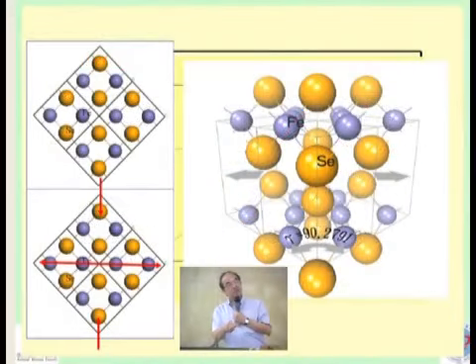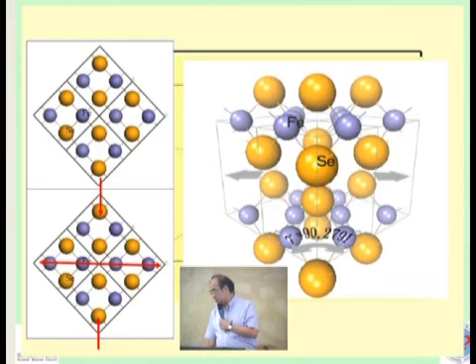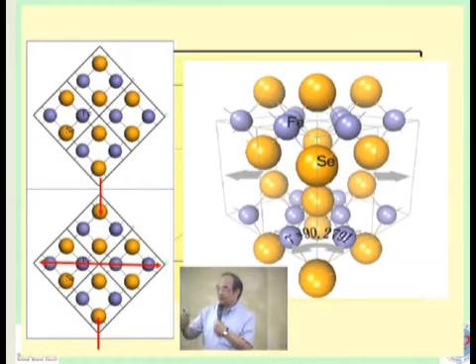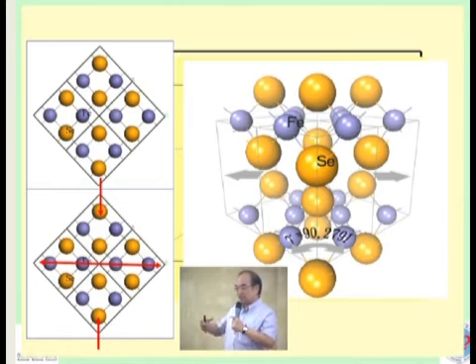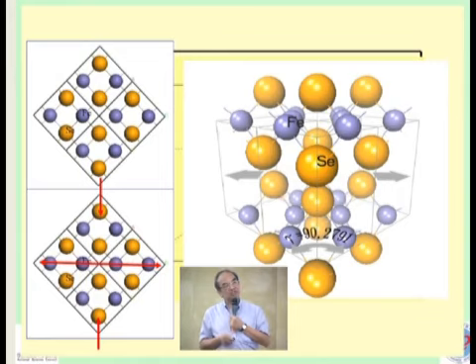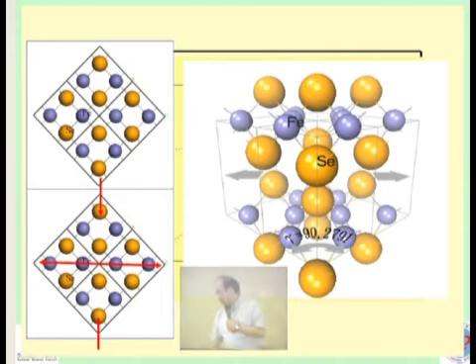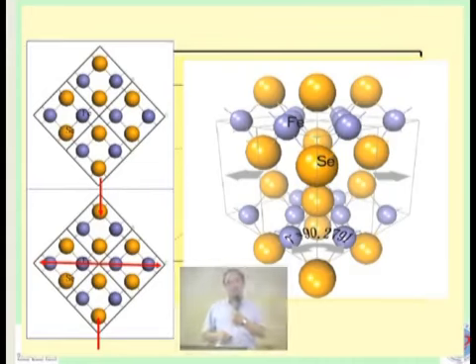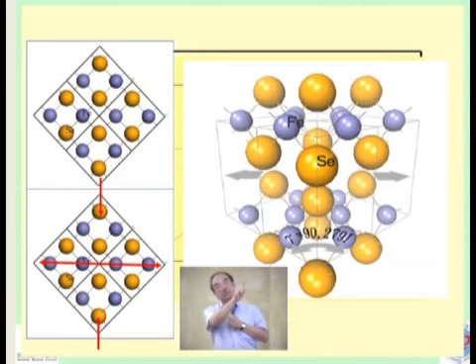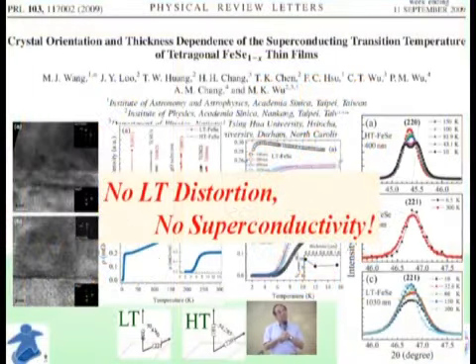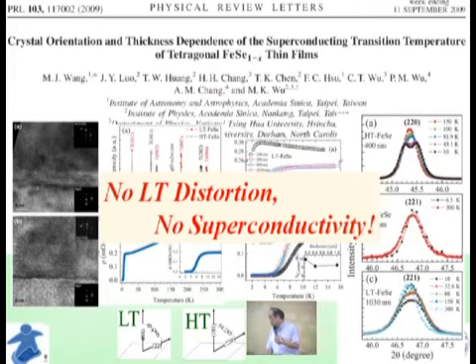Okay, so back again to this electrical data, we decided to look into the detail of the structure, and we found that this all goes back to Dr. Banner's original talk. There's the so-called Jahn-Teller distortion of the tetrahedron, right? It may not be exactly a Jahn-Teller distortion, but there's a structural distortion that appears at around 100 Kelvin. So the system is going from originally a square and somewhat stretched shape, and then you make this angle become larger than 90 degrees. And this is the feature behind all the key things I just showed you, the resistivity and thermal power. You know that no low temperature distortion means no superconductivity. Okay, this is our conclusion.